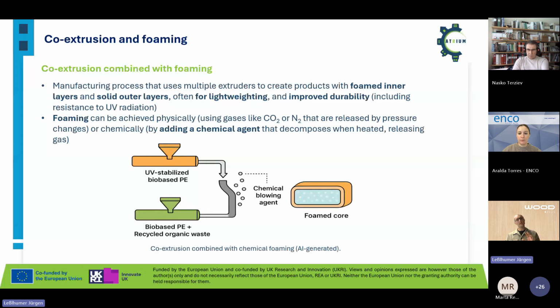And now we came to this special combination of the forming and the co-extrusion projects, which is a manufacturing process that uses multiple extruders. In our case, we're using two extruders to create products with a formed inner layer and a solid outer layer, and that enables lightweighting and also products with improved durability. For example, we can include UV stabilizers in the shell layer, and this forming can be achieved physically or also chemically, like we do in the ATRIUM project.